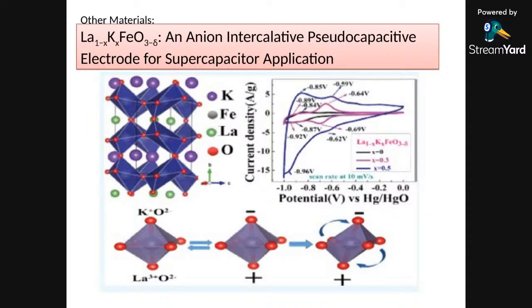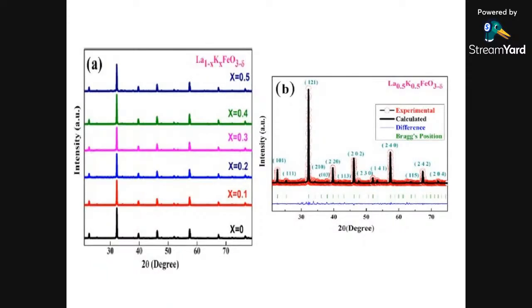What we have found as an advantage is that this leads to the oxidation of iron to iron 4+. So instead of only doing the iron 3-2 couple, we are able to actually get iron 4 to iron 3 and iron 3 to 2. So a two-electron exchange is possible, and that's what we have shown in this work. So this is the general doping pattern.